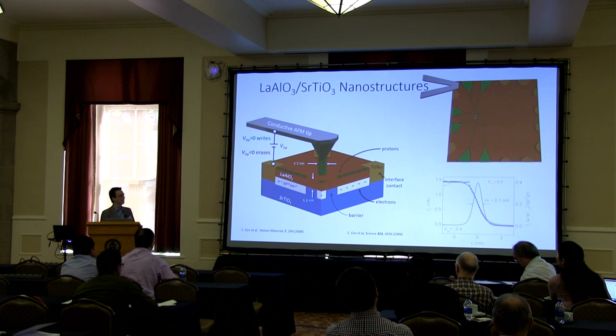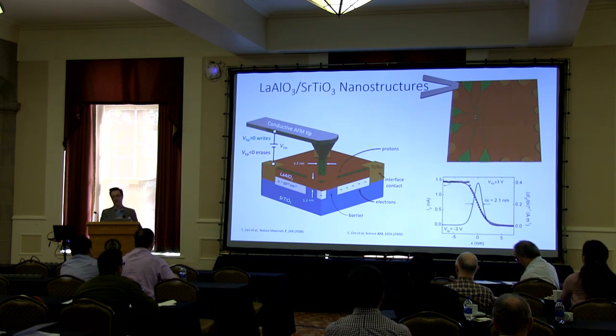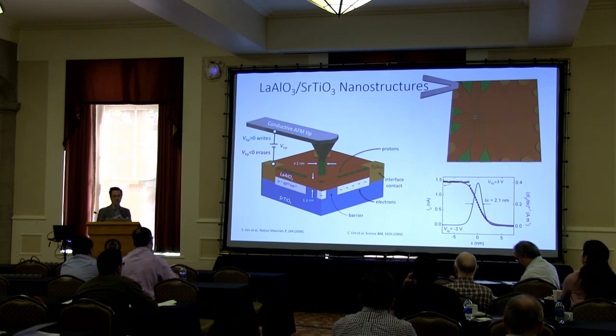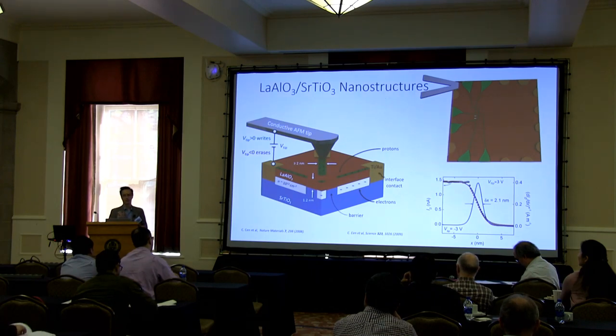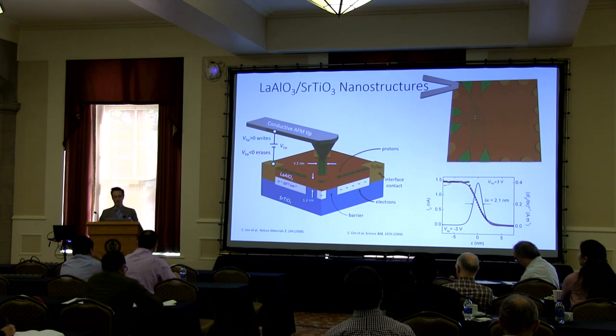This is an experiment that we published back in 2009 showing that once you write a wire, you can measure the conductance of the wire and then very simply cut across and erase the wire. And you see the sharpness with which you can erase it. It gives you a length scale, which is the width of this wire, which is about 2 nanometers.